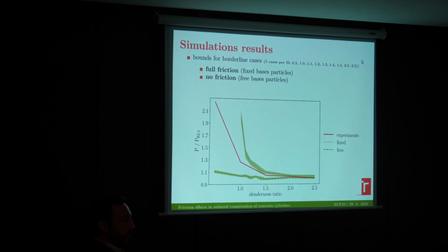Because the specimens were really small. Actually, it was 5 centimeters diameter and 2.5 centimeters tall, and from the results it looked like the confined compression zone acts really strongly if the particles are fixed.